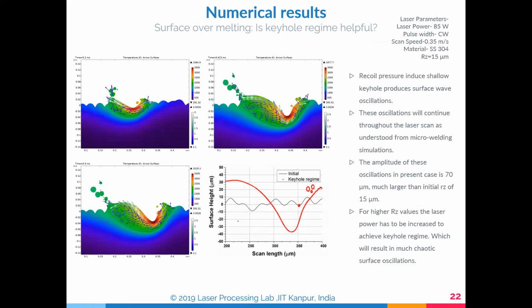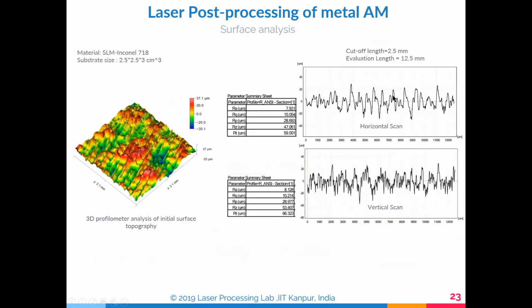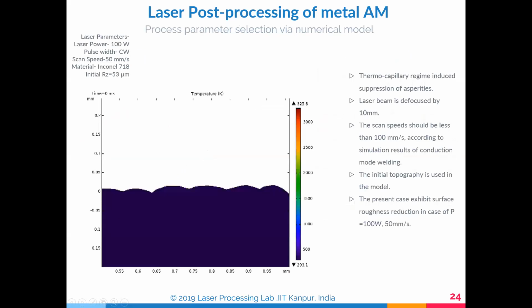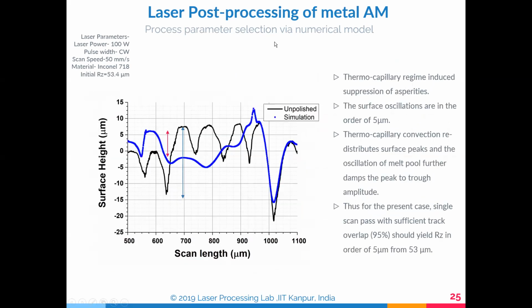The amplitude of these oscillations in the case of 70 microns was tried. And then we also tried to see the Rz values. So the cutoff length is 2.5, the evaluation length is 12.5. We try to see what the surface improvement is in the horizontal direction and the vertical direction, and what the improved output is. So this is the process parameter selection via numerical simulation.